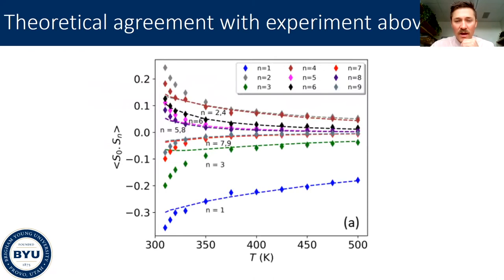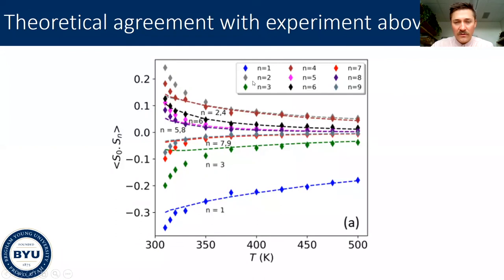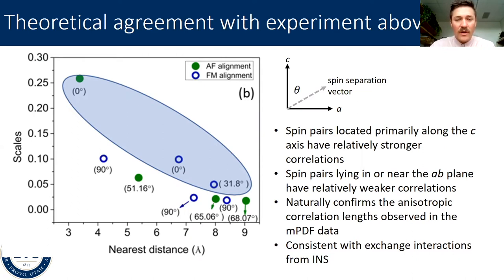Working with Julie Staunton and using DFT in the disordered local moment approach, we've been able to quantitatively reproduce the observed spin correlations extracted from our magnetic PDF data above ~350 Kelvin. We have a solid theoretical framework for describing the observed short-range magnetic correlations in MnTe, and the anisotropy — the fact that correlations are longer-ranged out-of-plane than in-plane — comes out naturally from the theory, which is also quite nice.